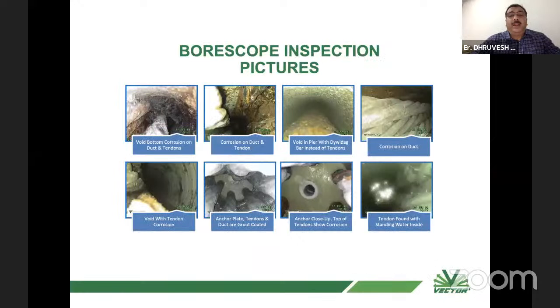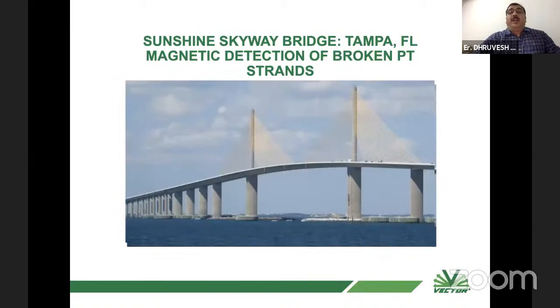And these are some photographs which show borescopic results, like void and bottom corrosion on ducts and tendons, corrosion on duct and tendon, like the duct is also corroding and the tendons are also corroding. This is a void in a pier with bar instead of tendons, corrosion in the duct, like various details you can get once you insert the borescope. So you can identify the tendons, you can have an impact echo test to know the location of the voids, and then you can insert the borescope and get pictures and know the condition. I will show you some examples. Sunshine Skyway Bridge, Tampa.